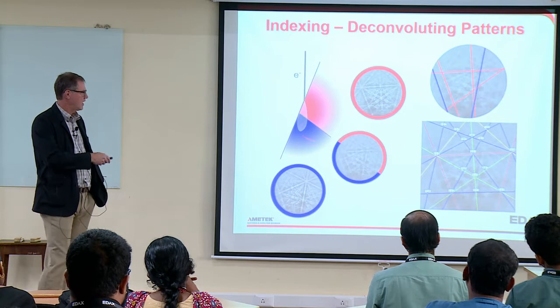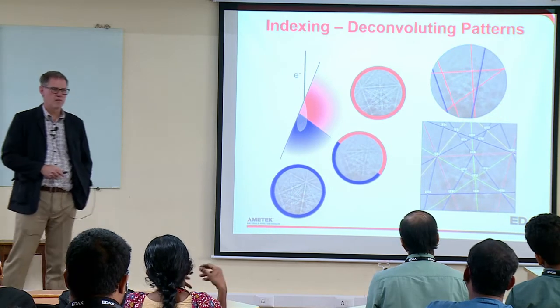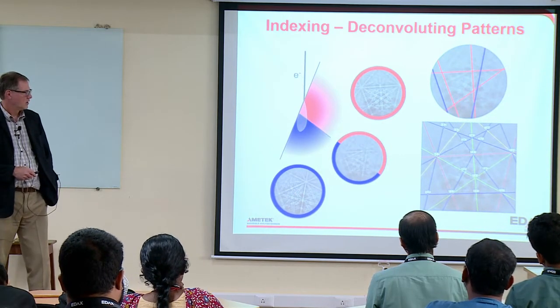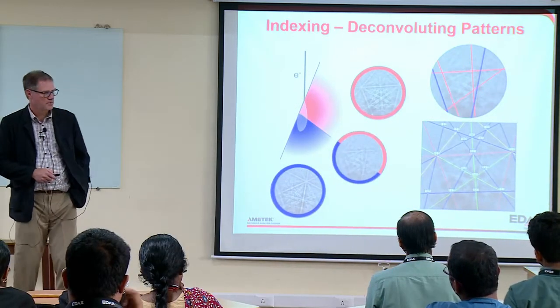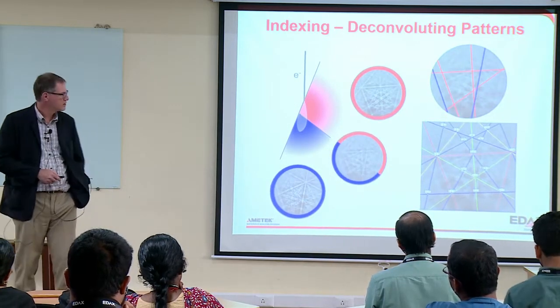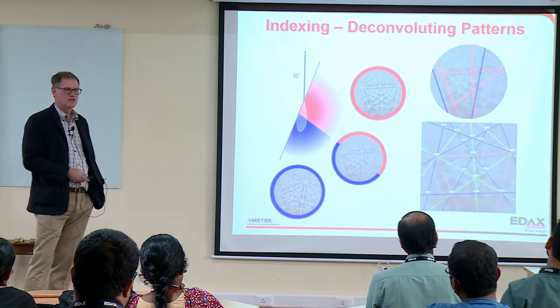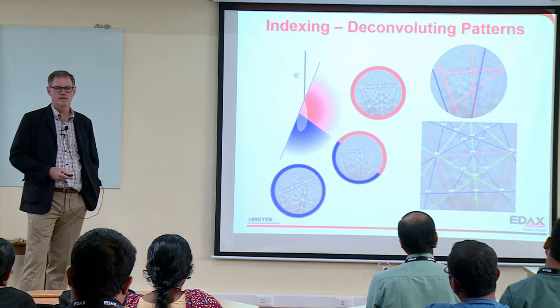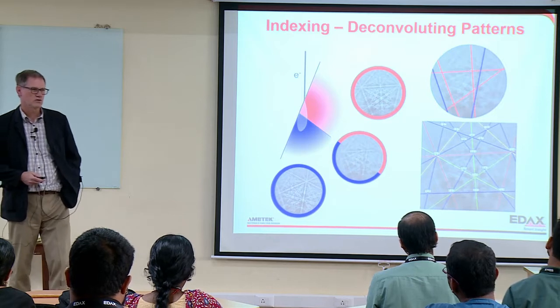And so EBSD can deconvolve bands at the edges. A little thing we've learned is that if we're having problems where we're smearing across grain boundaries, if we detect more bands than usual, that can also help us get a little bit better spatial resolution.